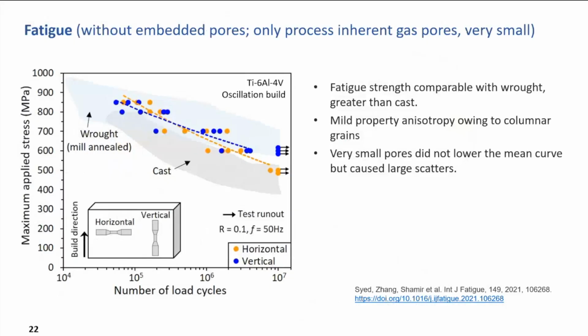So just switch to fatigue because I'm aware the time goes very fast. Fatigue without defects, and this is a quite high quality build. We did a scan, we did tomography, we did fractography, and confirmed maybe tiny process-inherent gas pores, but very, very small, smaller than the critical value.